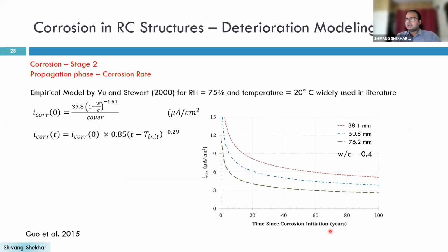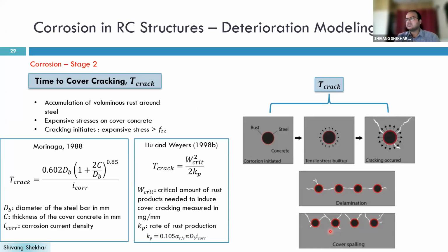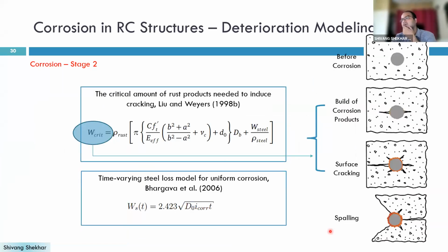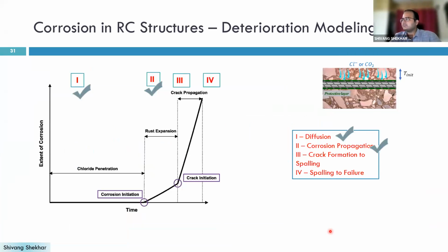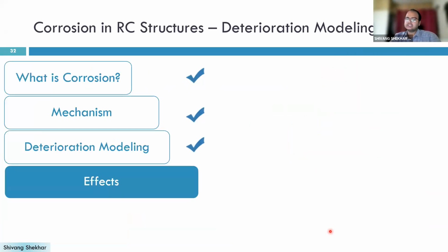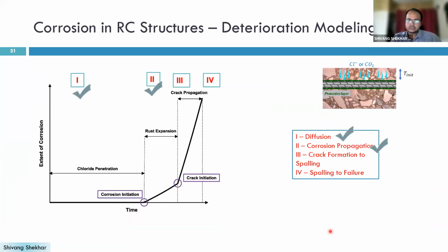Now, I will go back a little to the second stage of corrosion, the cracking of concrete. When the concrete will crack, there are again some models available in the literature that give formulations to calculate the cracking of the concrete. In addition, once the crack forms, there is more literature that gives the formulation for how spalling of concrete occurs and at what time. If we know the corrosion rate and the amount of rust formed, that helps us calculate the time when the spalling of concrete occurs.